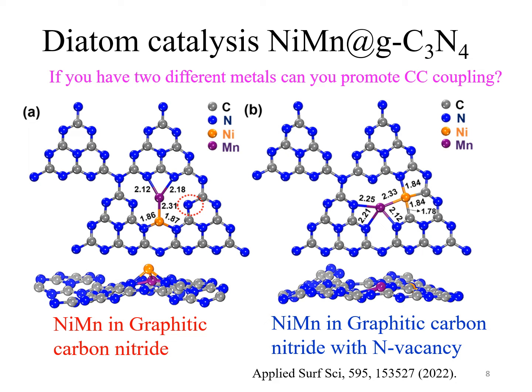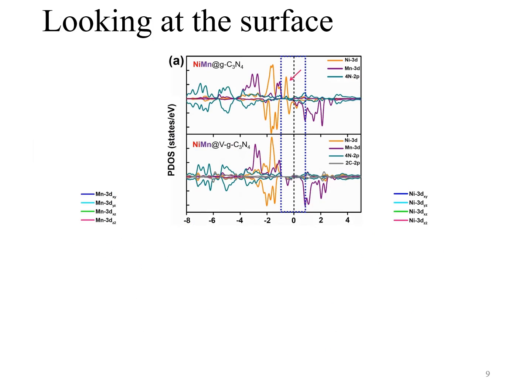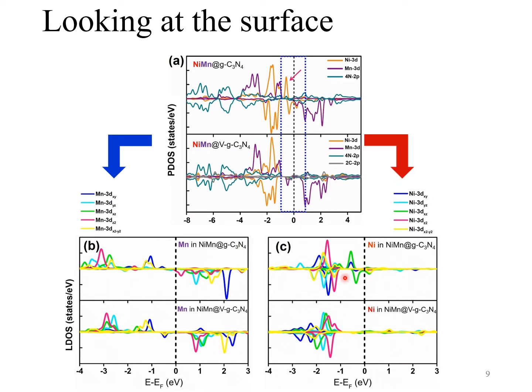So one question we had is, if we have 2 different metals, can we promote this CC coupling? And how is the electronic state of the 2 metals helping this reaction? So here we are looking at the projected density of states as a function of energy for our doping to pristine and doping to N vacancy graphitic carbon nitride. This is a bit confusing, so we just extract out the local density of states for the nickel and the manganese.